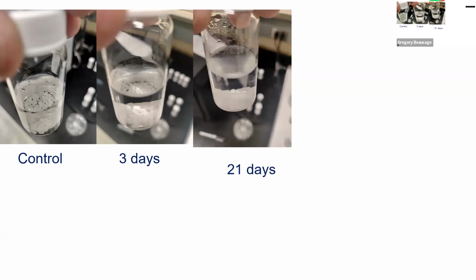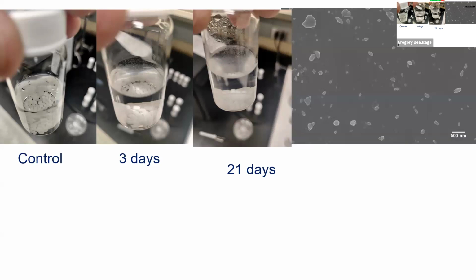It's 3 millimeter size particles in water. PET is denser than water, so it sinks to the bottom. No problem. And I stir the stupid thing. That's all I'm doing, is stirring. After 3 days of stirring, what do you see now? Some particles that you can see. After 21 days of stirring, what do you think now? You want to be drinking that? Put it under an electron microscope. That's what you're drinking: 500 nanometer size particles, platelet-like.